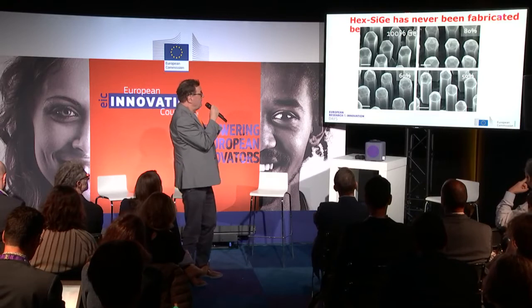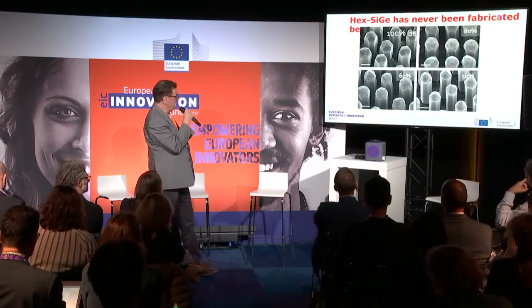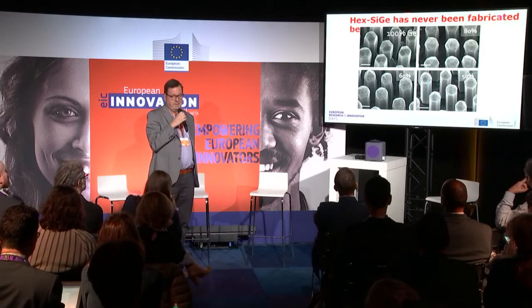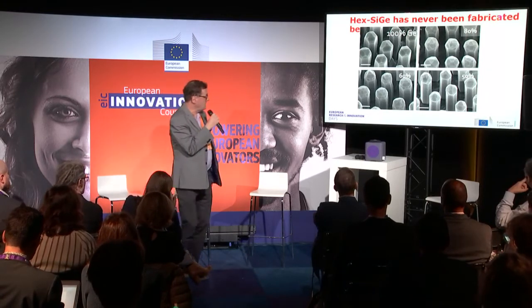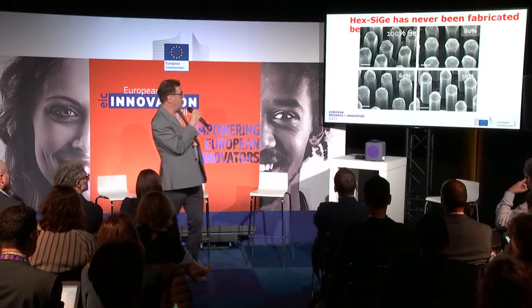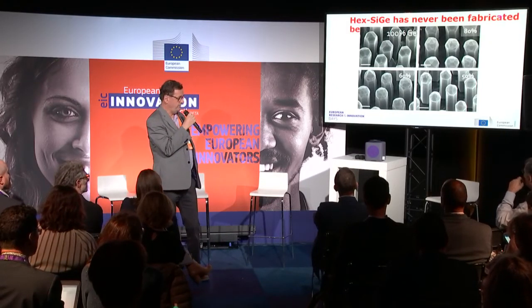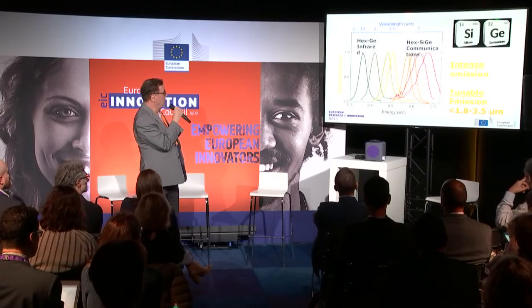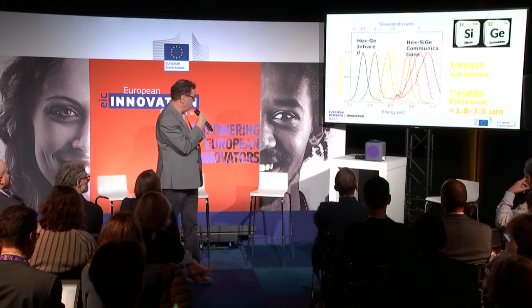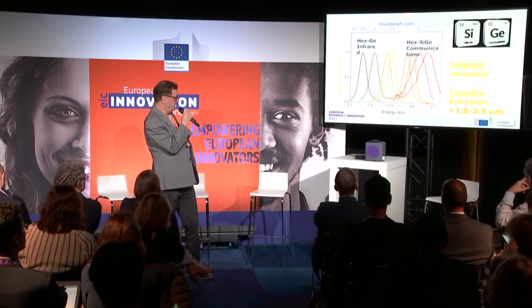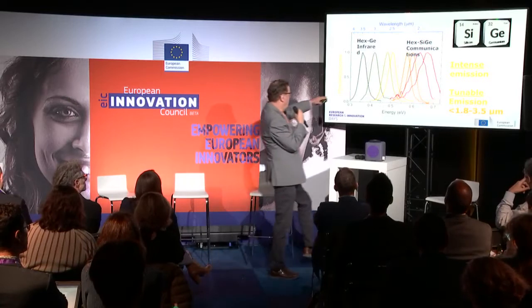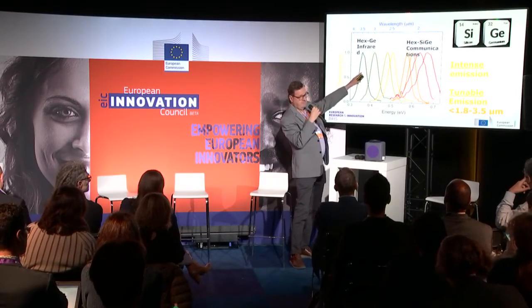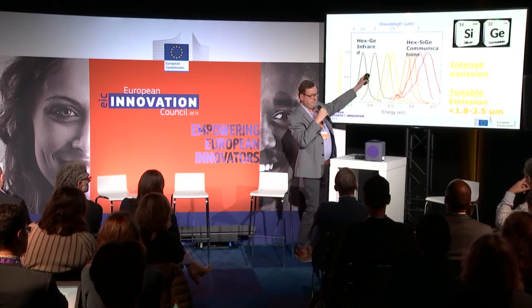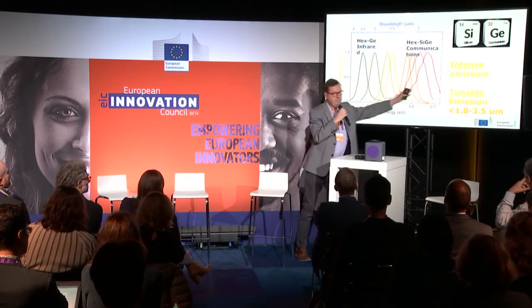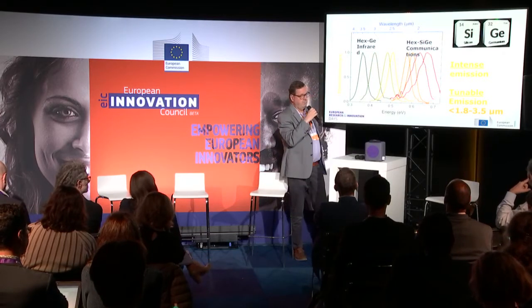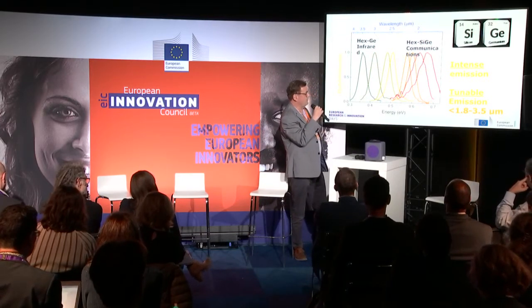So these are the first silicon germanium nanostructures. You should know that hexagonal silicon germanium has never been fabricated by anyone except in our consortium. And here you see we fabricated it with different material compositions. And once we have different material compositions, you see that we also have emission across a large wavelength range. So we have emission here at 3.5 micron with hexagonal germanium. That's maybe nice for infrared optical sensors. And we can continuously tune the emission down to 1.8 micron, which is nice for optical communications across short distances.